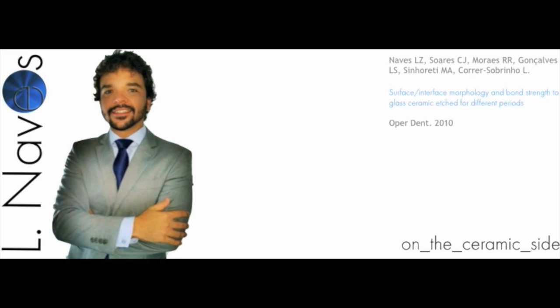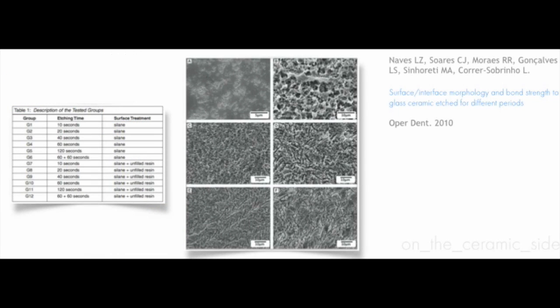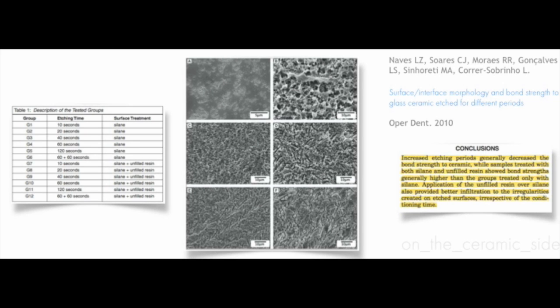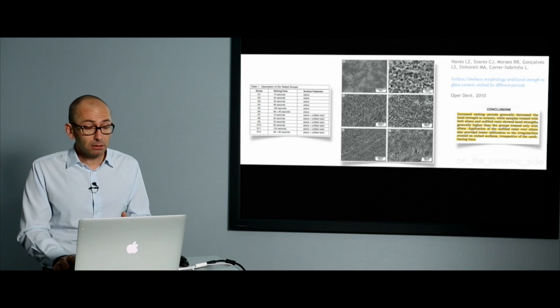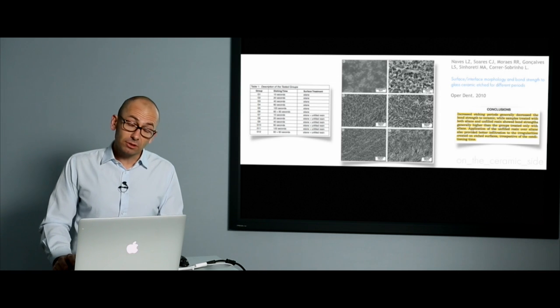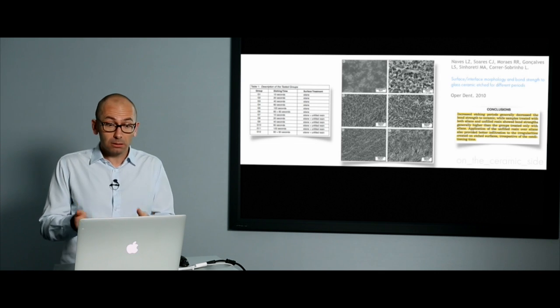So, on the other side now, on the ceramic side, what can we do to get an effective bonding? This is a very interesting study done by one of our mates of the group, Lucas Naves. Lucas is a young, brilliant Brazilian professor, and he did in 2010 a study with his team about the way we could condition the inner surface of the ceramic veneer to improve the bonding. So what they did, they took different etching patterns and different times for etching, and different coverings with silane and sometimes with resin. And they came to the conclusion that you don't need to increase the time of etching to get a better bonding, because you transform the surface and maybe you will alter the surface of the ceramic. So you have an ideal etching time depending on the type of ceramic that you are dealing with.